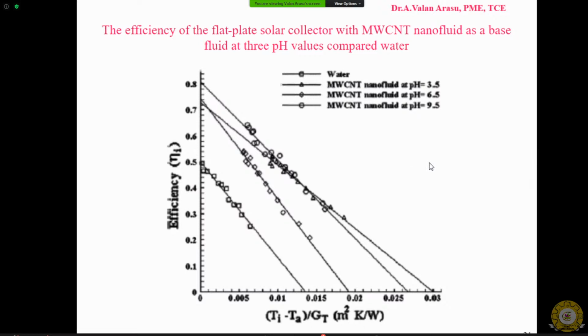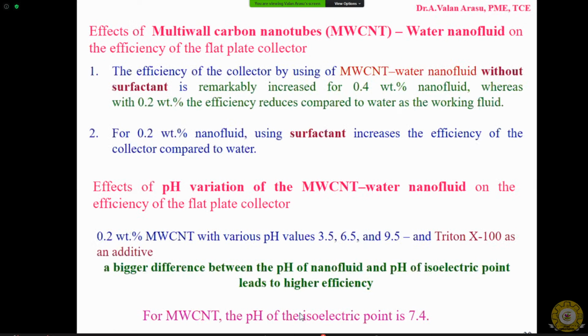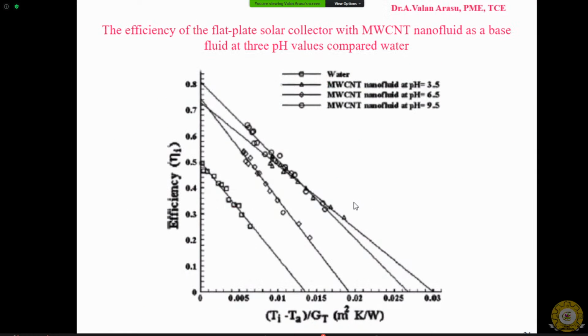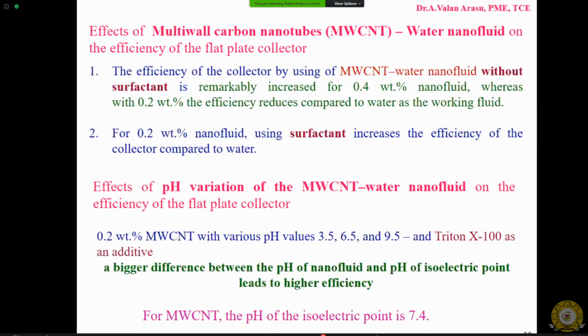Again, this comparison shows the pH of the isoelectric point is 7.4. You can see here this is for pH value 6.5, this is 3.5, and this is for 9.5. This pH value is close to the isoelectric point. So as we move further away from the pH value corresponding to the isoelectric point, which is 7.4.